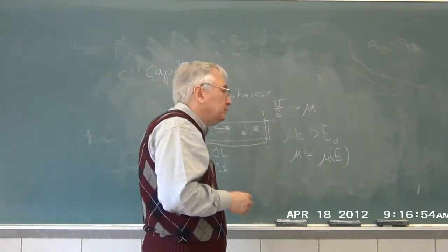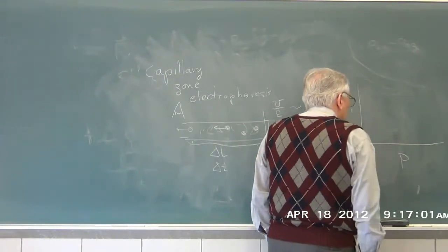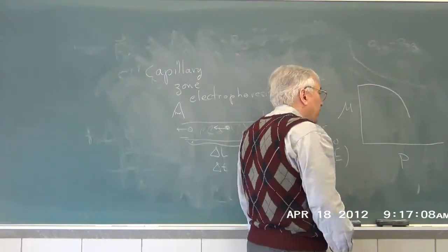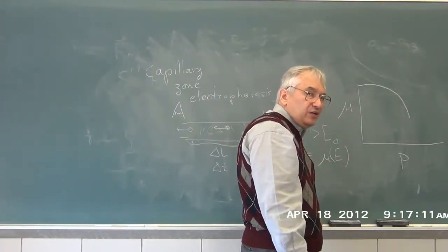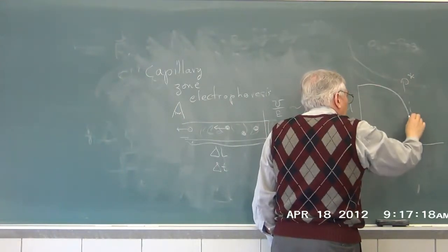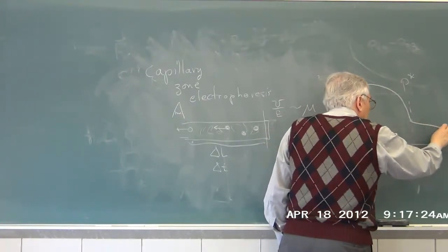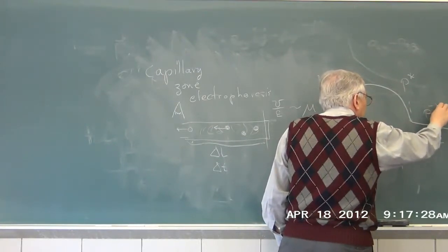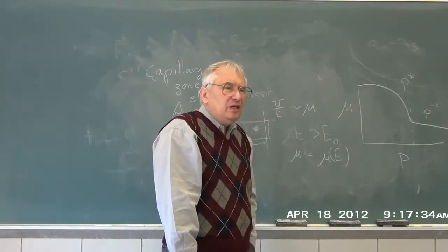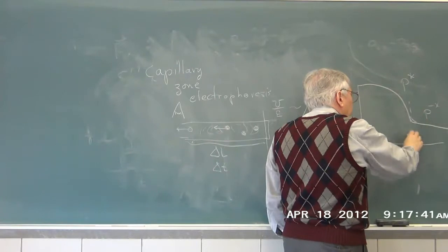Second, I can plot mu versus probe size. And what you see in the measurements is that mu falls as an exponential or stretched exponential in probe size until you get to a critical probe size. And above that critical probe size, which depends on the polymer concentration and the field, there is a very weak drop-off, which is close to a power law. The transition may or may not be perfectly sharp; if you do the probes at the same concentration, you can see what appears to be a few points of rounding.